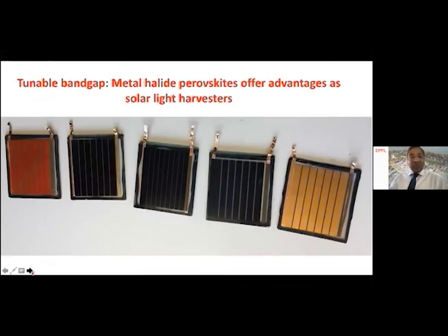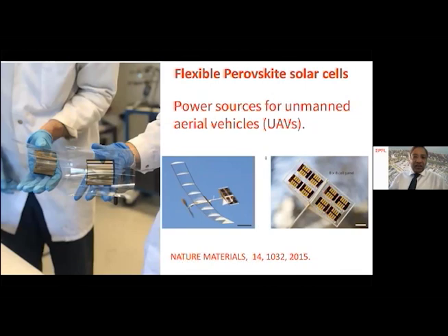As I mentioned before, we can tune the colors. Here is one color, replacing iodide by bromide, which gives you this type of color with a mixed halide. I'm not mentioning the exact ratio. You can get a brick red color, followed by different shades of black, and then you can also get a yellow color. So this is the tunability of color for building integrated applications.